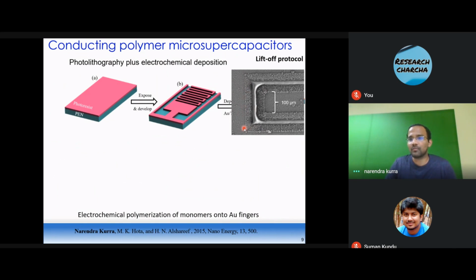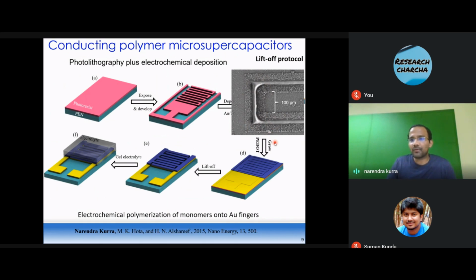But what we found is that since the electric field is enhanced at the edges, we see a lot of deposition happening at the edge of the fingers, and beyond a certain deposition we also observe shorting of the fingers. So what we did instead of doing lift off at this stage was to electrodeposit on the entire gold chip. Since the electric field is uniform on the entire substrate, we get uniform deposition of PEDOT everywhere across the area exposed to the electrolytic bath. And we performed lift off at this stage.